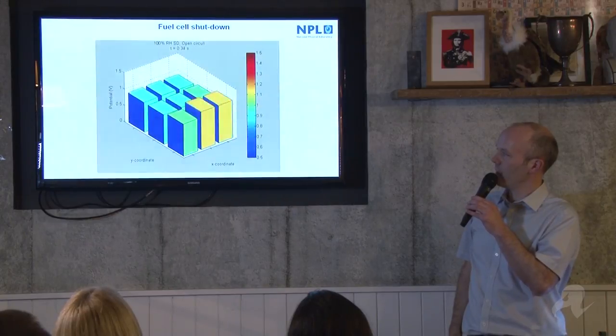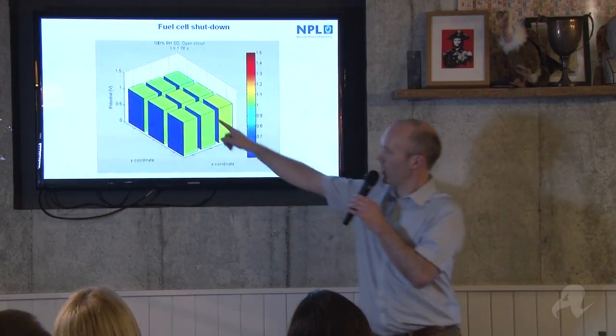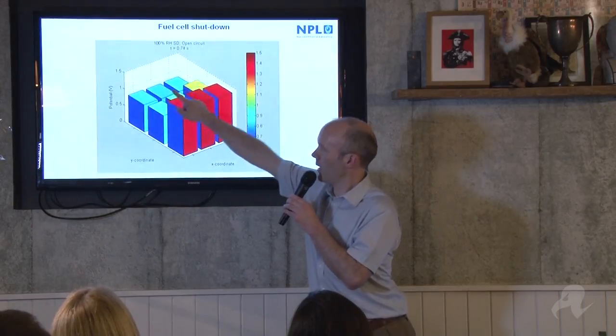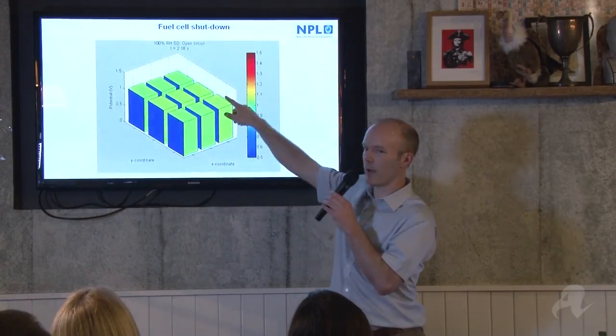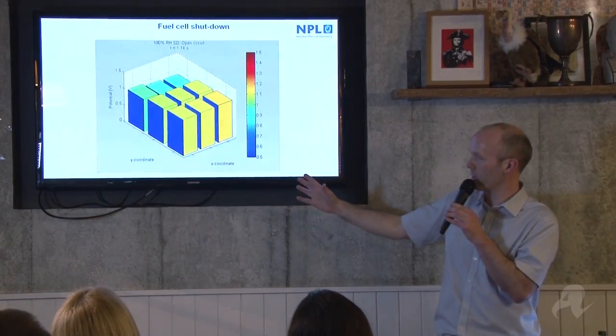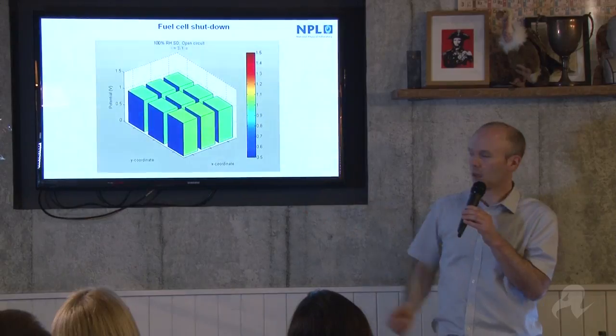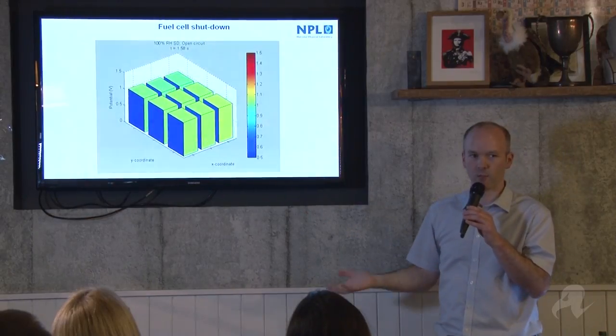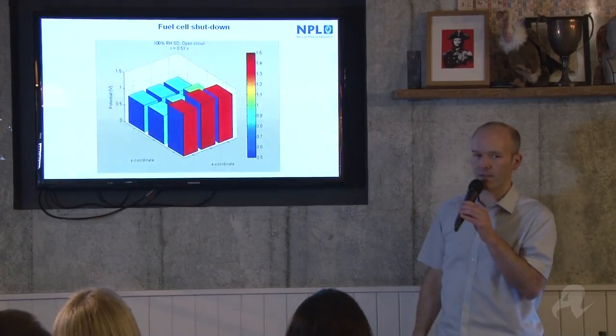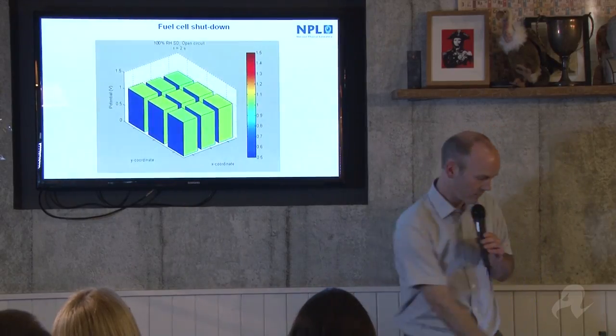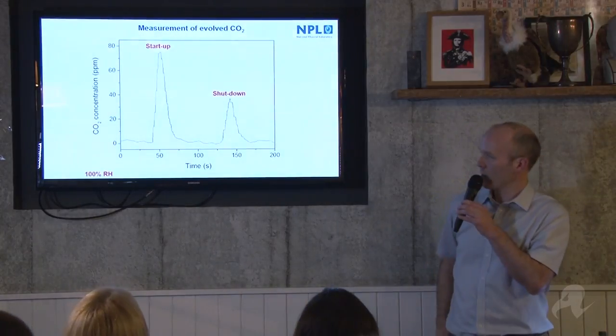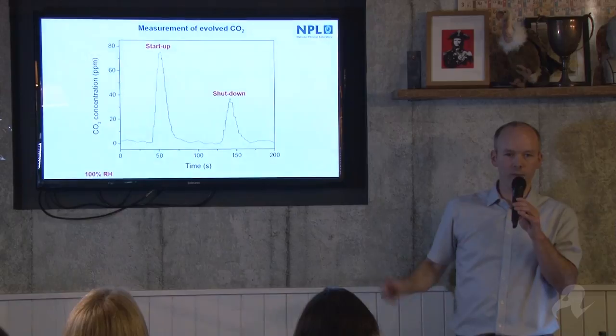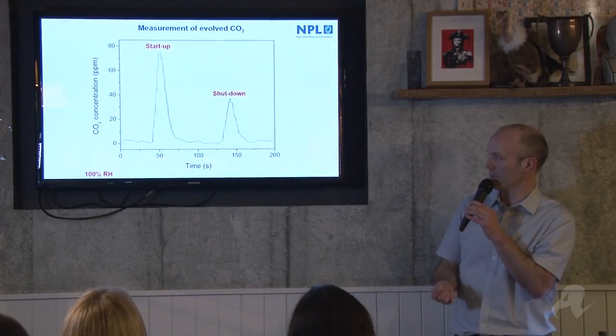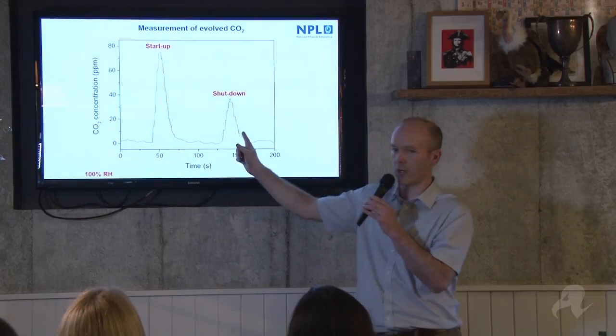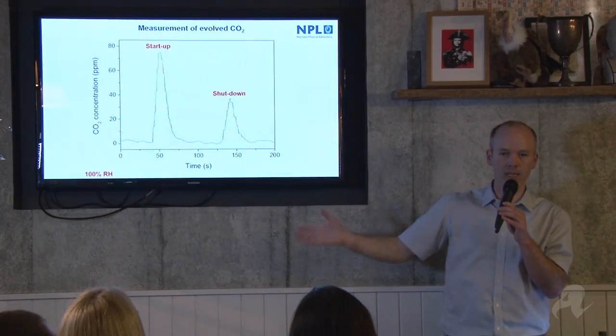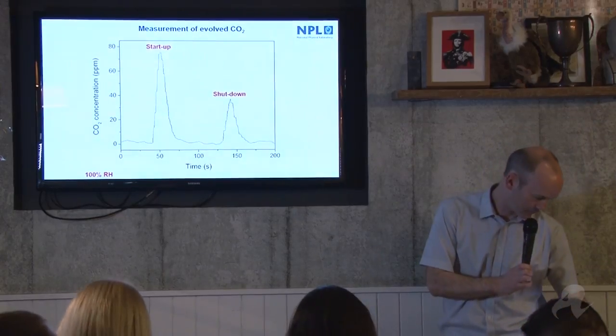So actually, in terms of where it's best to be in the cell, it's probably somewhere in the middle, as we see the most carbon corrosion. Remember, we have high surface area carbon supporting our catalyst material. And when we get corrosion of that carbon, we get loss of active surface area of the cell, which is one of the major reasons that the performance of the cell decays with time. We also measured the amount of carbon dioxide that was coming out of the cell as a result of this carbon corrosion. And we could see that startup was definitely worse than shutdown. And this tied in with the potentials that we were measuring in the experiment.